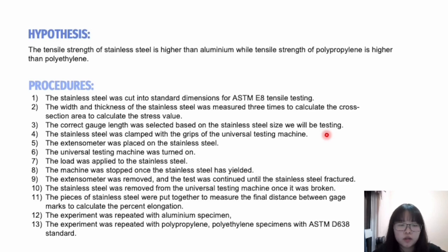And then the stainless steel was clamped with the grips of the universal testing machine, and the extensometer was placed on the stainless steel. The universal testing machine was turned on, and the load was applied to the stainless steel. The machine was stopped once the stainless steel had yielded, and the extensometer was removed. The test continued until the stainless steel fractured. The stainless steel was removed from the universal testing machine once it was broken.